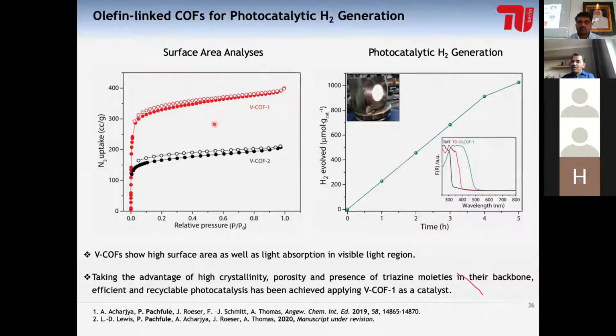And most importantly, even this triazine-based COF showed absorption in visible light. And when applied for photocatalytic hydrogen generation, this material showed efficient hydrogen generation. So just taking advantage of high crystallinity, porosity, and the presence of triazine moieties in this COF, we have shown the utilization of this COF for photocatalytic hydrogen generation, which is really a smart material, and we can do different catalysis to generate hydrogen, which can later be used as a fuel in fuel cell cars.